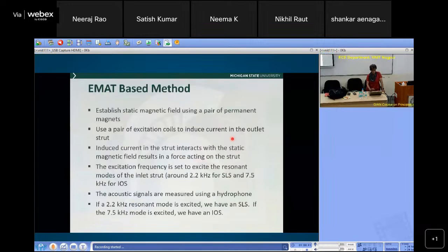We want to detect those kinds of cracks. So we basically use an EMAT method. We induce eddy currents in the ring, and then we apply another external field, and we set the whole heart valve into vibration. And then you can just use a stethoscope, a digital stethoscope, to look for defects. When there is no crack, the resonant frequency is like 7.5. When there is a crack in that heart valve, the resonant frequency goes to 2.8 or something. So we can just look at a spectrum and determine if there's a crack or no crack.